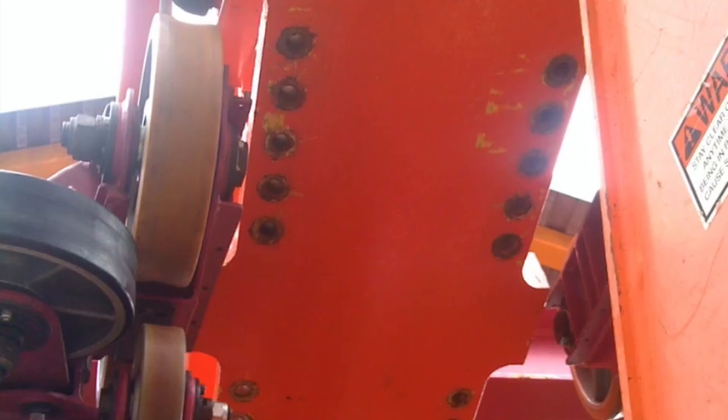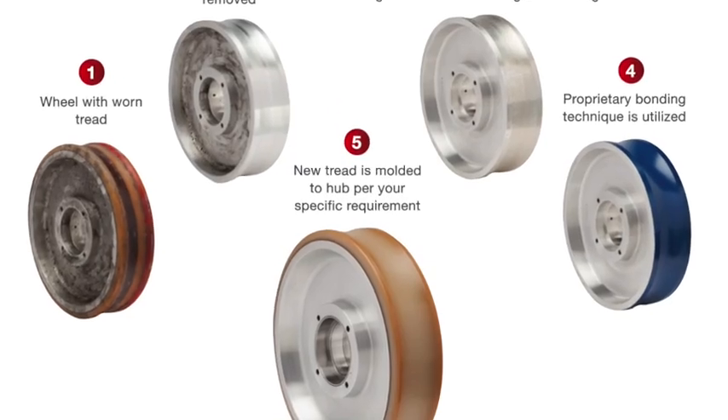What happens is that these wheels that don't wear that often don't cup excessively. Notice how this one's pretty flat on top — some of the other wheels you've seen are more like a U-shape because they're cupping. When wheels don't cup to the track and they stay like this, they get relatively little wear at all and can just sit there and run for an indefinite period of time. But after three or four years in service, the urethane becomes old, starts to dry out and harden, and it's prone to cracking much faster. Then you can have a complete delamination. On regular trains you don't see that that much, but if you're talking about things that have wheels crushed to the track with a spring-loaded mechanism, you see that sometimes on those.